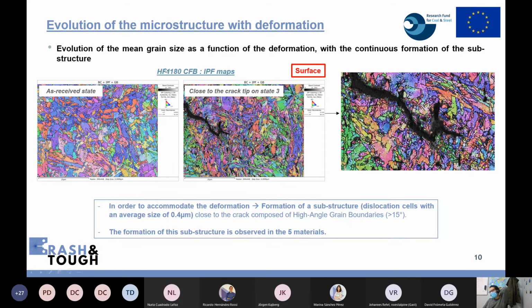Here we see through the IPF maps the evolution of the mean grain size as a function of the deformation. This is the as-received state, and this is the state 3 close to the crack. And what we can see is that close to the crack, a lot of new grains with high angle grain boundaries are formed. And so we have a formation of a substructure with dislocation cells of an average of 0.4 micrometers. And this formation of the substructure is observed in the 5 materials.